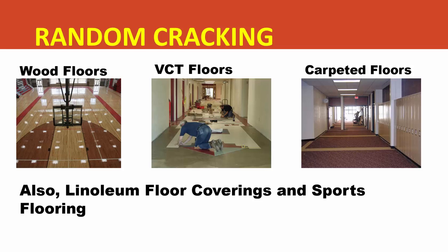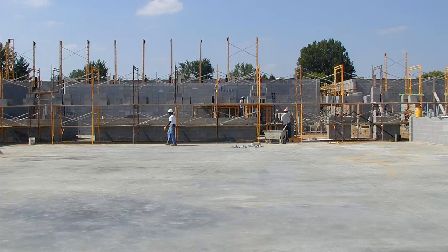Contraction joints in slabs-on-grade are aesthetic improvements. Without them, concrete would random crack. The concrete floor in this photo will be allowed to random crack. While jointing is an aesthetic method of putting drying shrink cracks where the designer prefers them, the curling that results is a problem for the installation of many types of floor covering. Allowing concrete to random crack under carpet, VCT, linoleum, and wood gym floors would improve the installation of these floor coverings by avoiding curling altogether. Any random crack design should incorporate welded wire reinforcement to keep the cracks held tightly together, especially in long narrow ribbons of concrete.